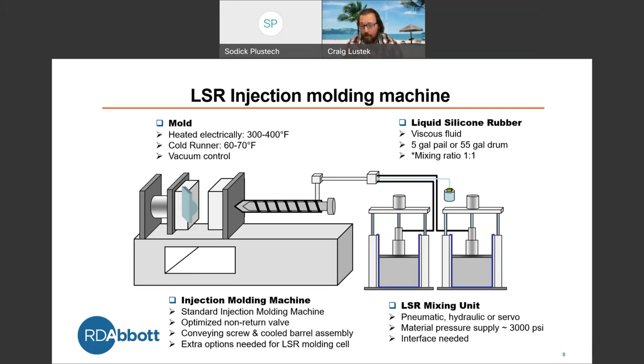Our liquid silicone rubber is a viscous fluid. Again, it comes in 5 or 55-gallon containers. And we want that mixing ratio to be 1-to-1. I have an asterisk there because depending on the type of part you're manufacturing, depending on the type of LSR, we can go away from that ratio about 5%. But we want to make sure that the general properties are still within that specification you need as we're running.